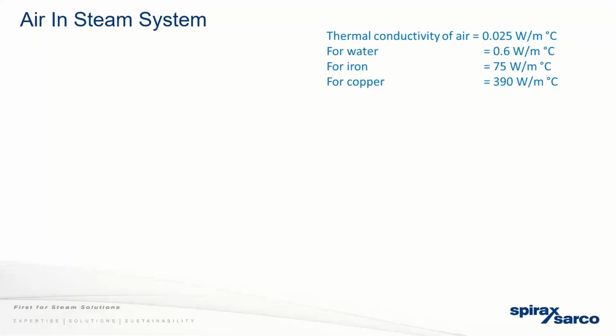The other issue with having, apart from oxygen being corrosive, is having air in the system itself. When you have air in the system, air is a really good insulator. As you can see from the values for thermal conductivity on the right over there, thermal conductivity of air is very low, so it makes a really good insulator. And you can see for copper, it's significantly higher.